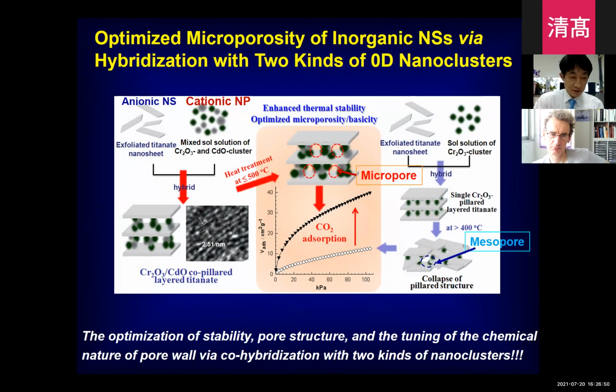Some old data, but I show it to show the advantage of X-ray absorption spectroscopy to characterize such highly anisotropic materials. Previously, we synthesized the chromia-pillared layered titanate by self-assembly between exfoliated titanate nanosheet and positively charged chromium oxide clusters. But for application as a gas absorbent, we have to maximize the microporosity of this material. So we came up with the idea of restacking with two different kinds of nanoclusters having different particle size. In that way, we can build up a robust pillar, and maximize the microporosity of this material.